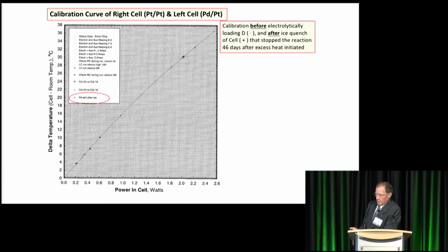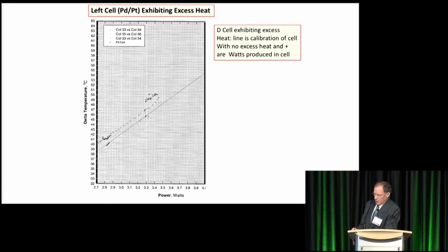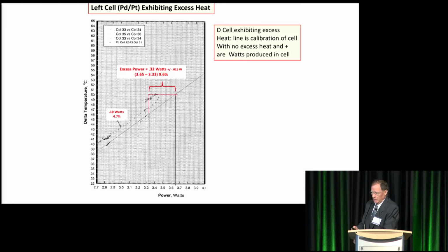This is a data set, again, the same data set, the calibration curve, but at the end of the experiment where we had seen excess heat, and then I said to myself, am I still on the calibration curve? So the large crosses here that you see were taken after the experiment to confirm that we're still on the calibration curve. During the experiment, the cells ran higher than that calibration curve. Actually, I need about 5 more minutes. Right here shown. And then that is an excess power of about 0.3 watts. Doesn't sound like a lot, but the specimen is very, very small.